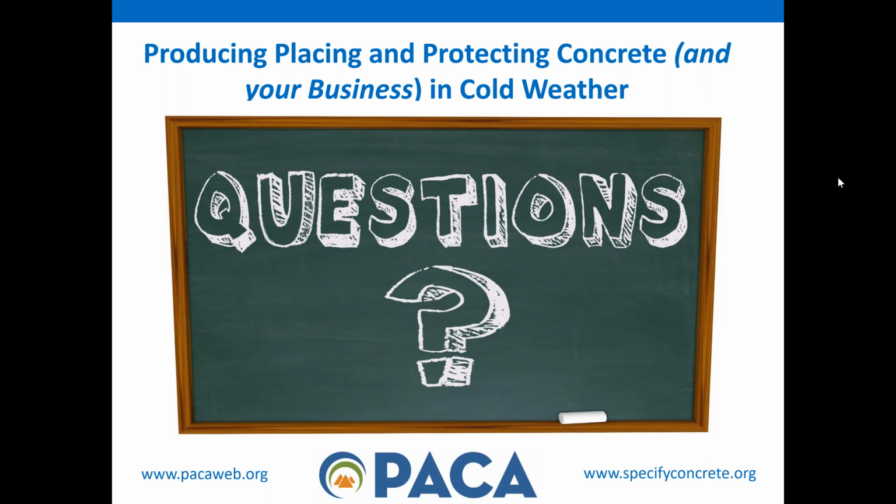One of the talks, and I was fortunate to listen to Ken Hover address the issue, he brought up a problem without a solution: in colder weather, we want to maintain moisture in there so it gains strength. The problem is when we maintain moisture in and it gets cold and is subject to early freezing and thaw cycles, we can hurt the durability of it. So it's a very, very difficult thing to maintain durable concrete when it's subject to early age freezing and thaw cycles without maintaining it above freezing. If you're inside a building, you can maintain everything above freezing. Building something outside, that's very difficult. He just brought to bear the problems we have out there, both maintaining moisture for strength gain and, at the same time, maintaining temperature and not causing early age damage from freezing or thawing.